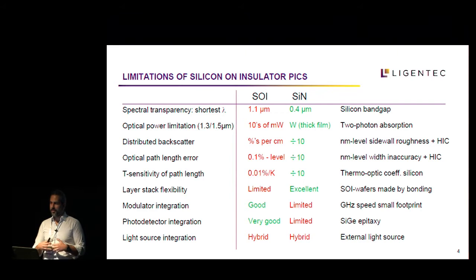Regarding the losses of the material, some of the benefits which make it easy to scale up is that you have a lower index contrast compared to your cladding and compared to silicon. So it reduces your distributed backscattering by a factor of 10. It decreases the optical path length error by another factor of 10. At the same time, the material is less thermally sensitive. So if you need to have some thermal designs, it drops the power consumption that you need by a factor of 10. Of course, if you want to tune such a material, you need to put 10 times more power, which is a trade-off you need to make in the design phase.